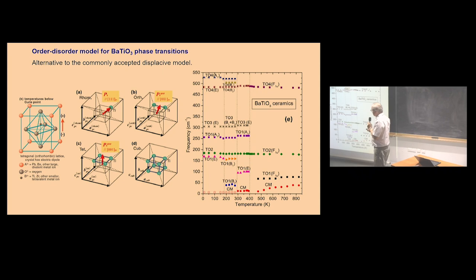In X-ray you see just the middle position, but actually there is such hopping which is responsible for the central mode. And in tetragonal phase, you have displacement of titanium along z-axis, and in this case you can imagine you have hopping only among 4 positions. And again, you can see some central mode.